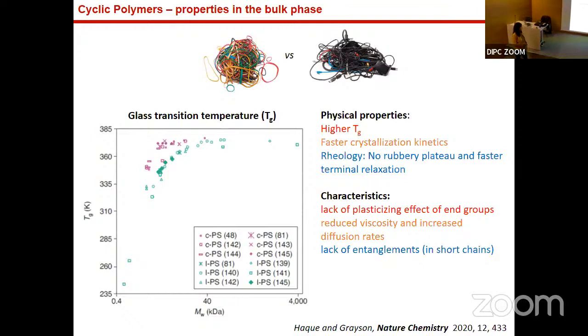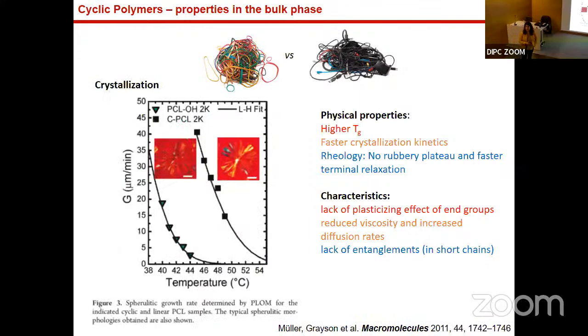and of course they have no more effect on the glass transition temperature. There is another property, which is crystallization. Researchers have found faster crystallization kinetics in these cyclic polymers. In this case, it's cyclic polycaprolactones, and the researchers explain these results by the reduced viscosity of the cyclic polymers in the bulk phase, which increases the diffusion rates and favors the crystallization of these cyclic polymers.